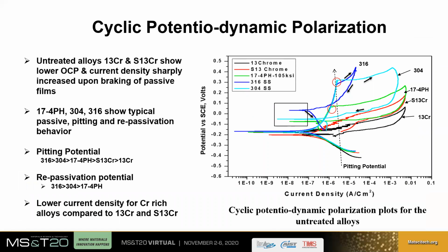Now let's discuss the polarization study results of the untreated alloys first. Results are plotted together for comparison. This plot is of current density and potential. As we can see from these plots, untreated alloys like 13 chrome and super 13 chrome show lower open circuit potential, and the current density sharply increases due to rupture of the inherent passive layer, generally the chromium oxide layer on the surface, which is indicated by serration in the plots of 13 chrome and super 13 chrome material, whereas 17-4 PH, 304 and 316 still show typical passive behavior, and pitting and repassivation behavior.